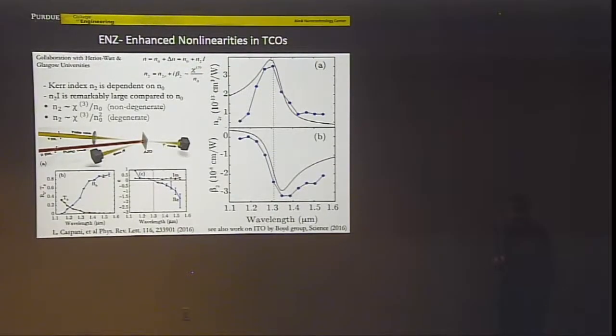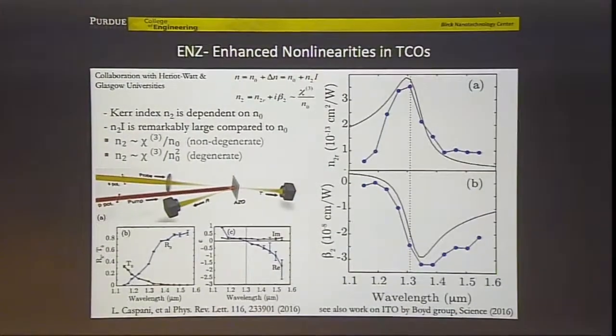nonlinear susceptibility, chi3. This is a chi3 process, but it has the linear refractive index in the denominator. So the linear refractive index is the square root of epsilon times mu. If my dielectric permittivity goes to 0, then the refractive index goes to 0. And then you have a quite unusual situation. The linear term, which always dominates, with the nonlinear term being small, provides only these small nonlinear corrections. Actually, the linear term goes to 0, so that the nonlinear term is larger than the linear one.